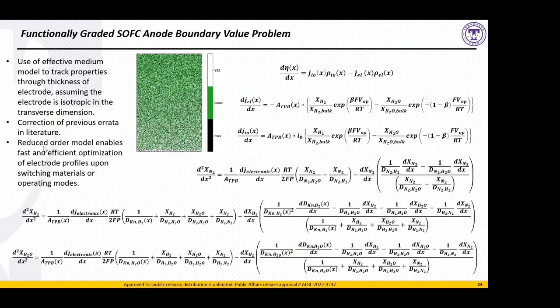Doing all this, we finally form a boundary value problem, and this defines the electrochemistry for the electrode. Here we just have at the top the expression for the overpotential. We have the expression for the electronic current density, the ionic current density, and then here defined the gas diffusion for an anode with a hydrogen nitrogen steam mixture. And you see the two expressions for the electrochemically active species and the inert species, the nitrogen, and how those expressions change.